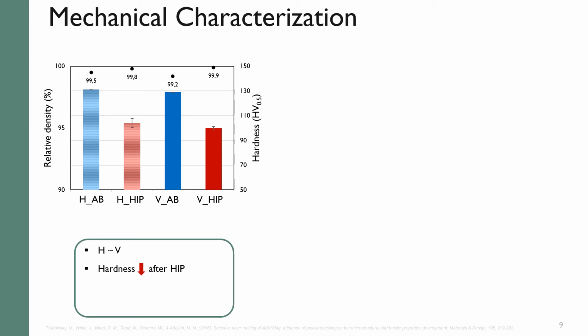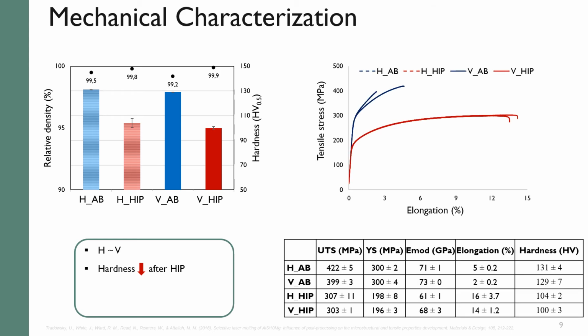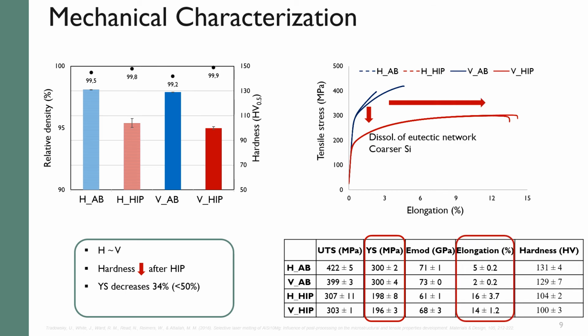And when we have a look at the tensile test results, we can again see that tensile behavior of horizontal and vertical samples are very similar, except for higher elongation of horizontal samples in the as-built state, which can be related to the porosity amount and the orientation. There is a decrease in yield strength around 34% due to the dissolution of eutectic network and coarser silicon after HIP, while elongation increases significantly thanks to reduced porosity.